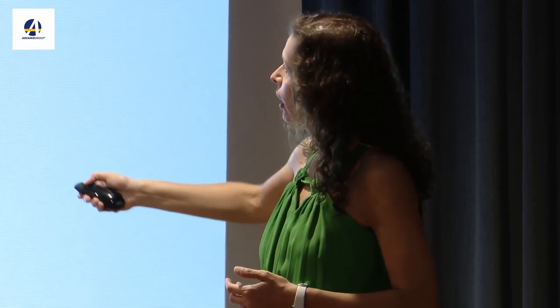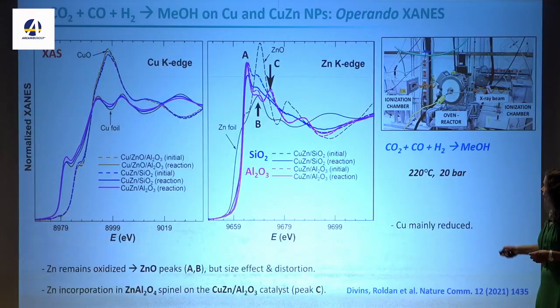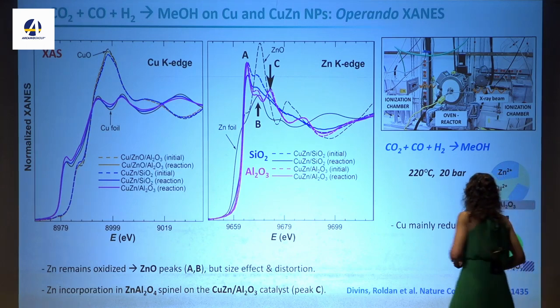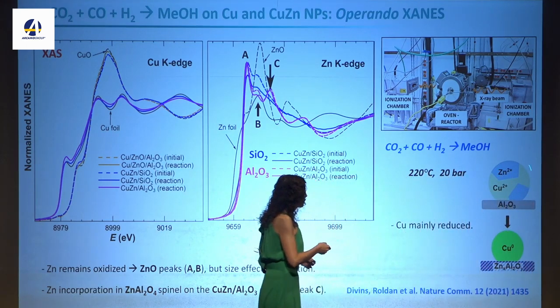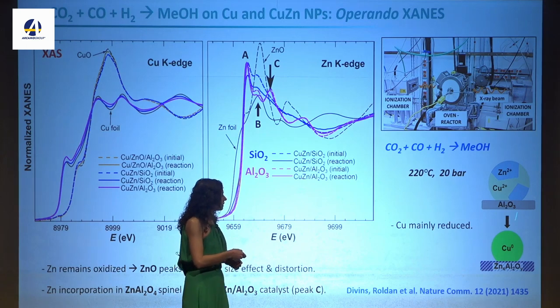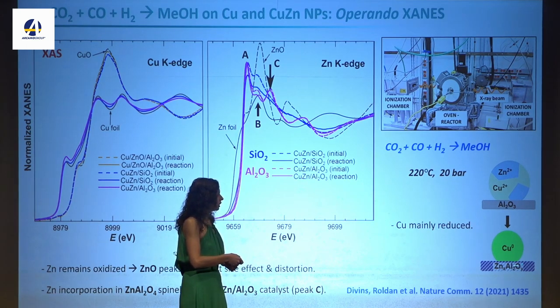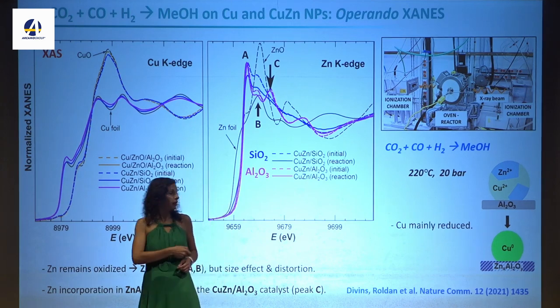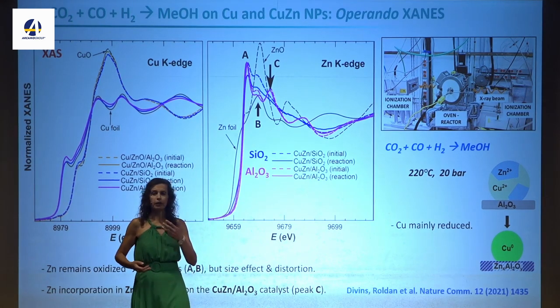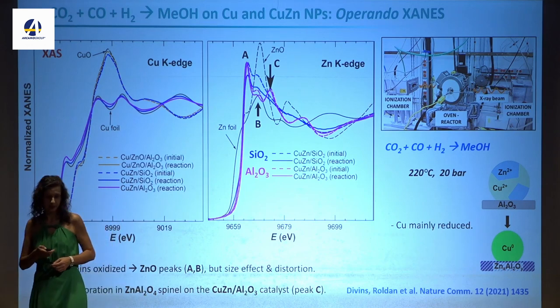But if you compare with the same particle size and the same composition on alumina, this third peak appears here. And when you look at the reference, you realize that this indicates the incorporation of zinc into the alumina. So you make this spinel, this zinc alumina spinel, and this is actually the catalyst under reaction conditions when you have alumina support. So with alumina, you start with something like this, and then unfortunately you lose all the zinc. It goes and becomes incorporated into the alumina, and you end up with a mainly metallic particle. This is the catalyst that I was showing you before that makes a mixture of methanol and dimethyl ether.